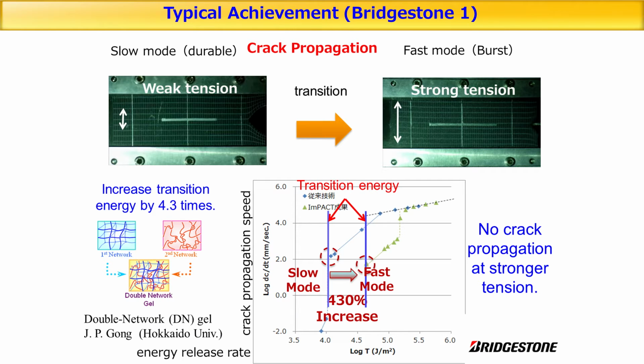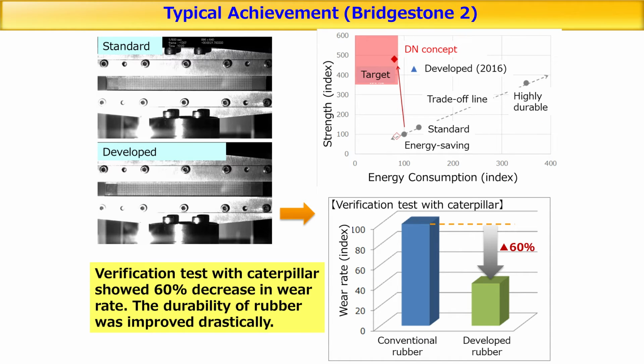The next example is the one we worked on with Bridgestone, which is a tire manufacturer. They wanted to create tough tires or tough rubber and aimed to reduce the energy consumption of the tire by half. The rupture energy has increased by about 4 times. And they applied this to the caterpillar. There's a rubber caterpillar. They tested it on a rough road, and wear was reduced by 60%.